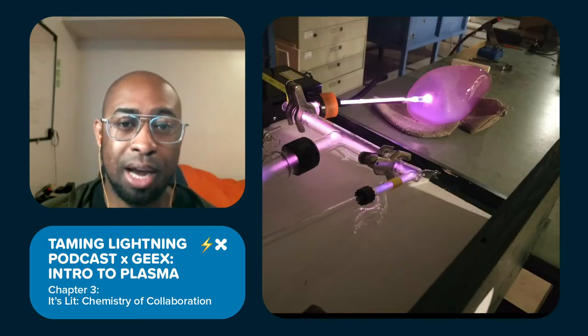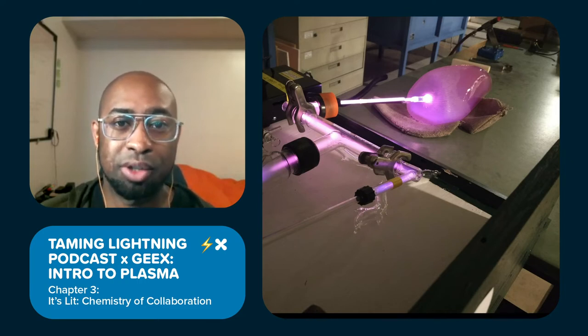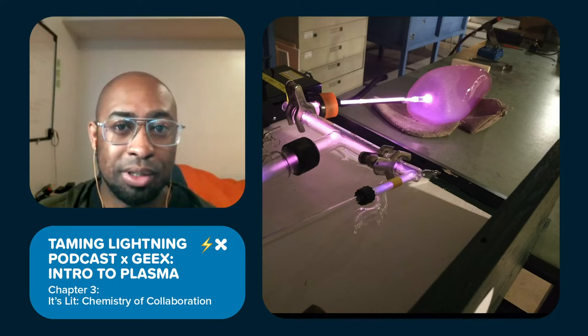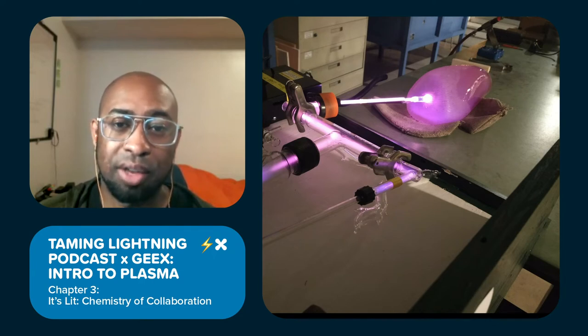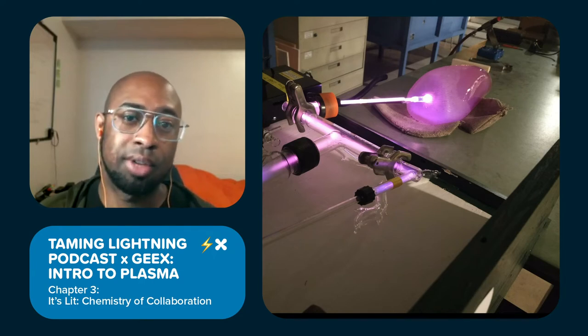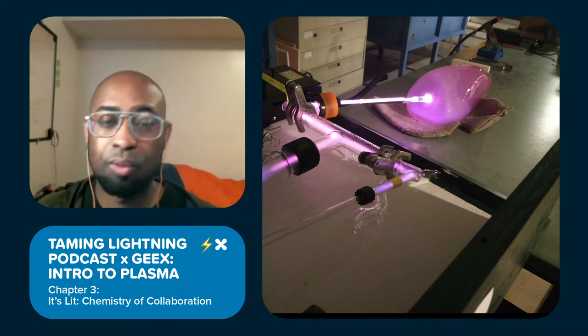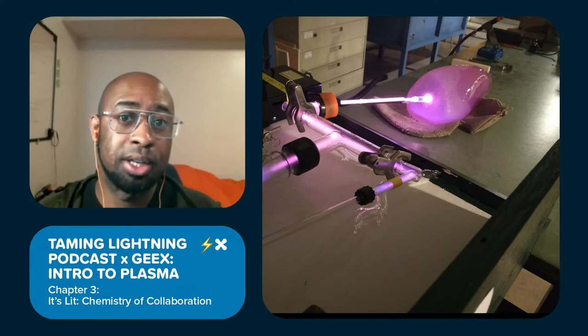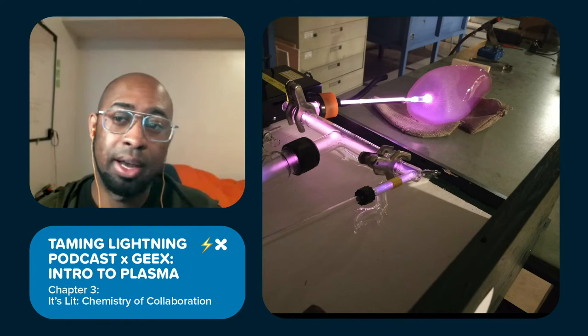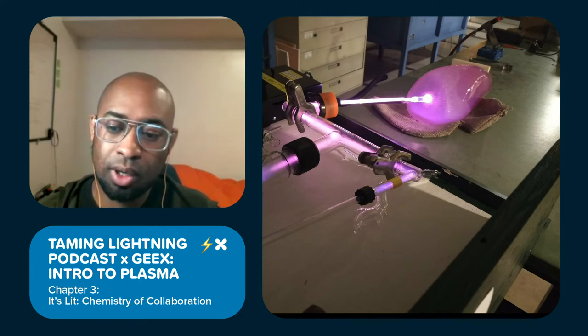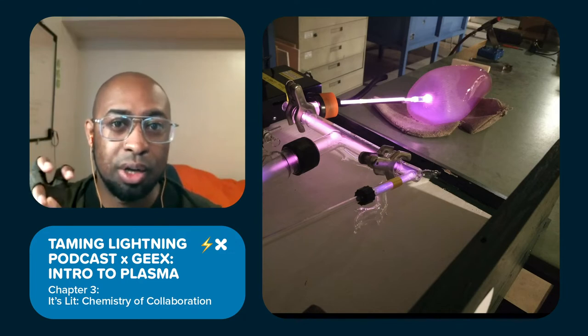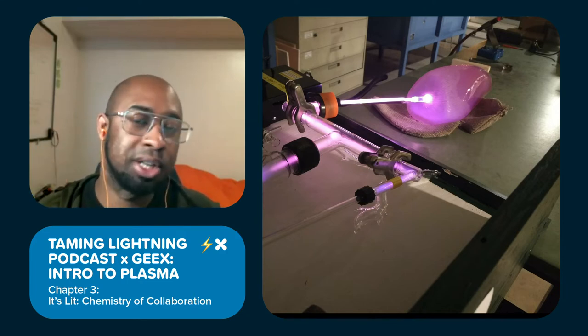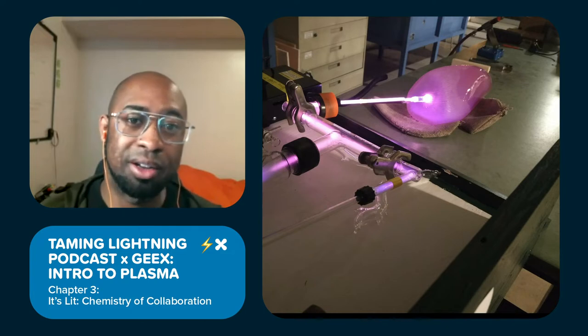You also want to avoid flashback whenever possible. You don't want to have a highly conductive fill in your manifold from your plasma transformer. If this happens, turn off the transformer immediately, take note of what you saw, and add more gas as necessary, or turn down the strength of your transformer. You see, the risks of this happening can damage O-rings in your glass manifold. This can damage the gauges that are hooked up to it, or it can damage the metal components that work to seal and hold back the gases in your tanks. So it's very important that you don't let this cold plasma affect or damage any of the other components that it should not be interacting with.